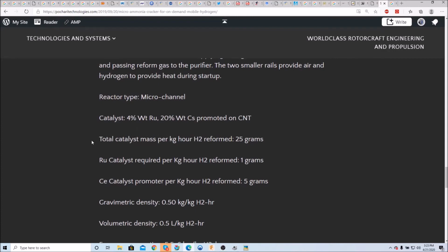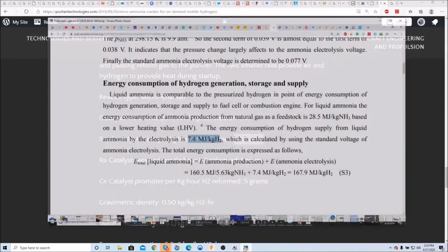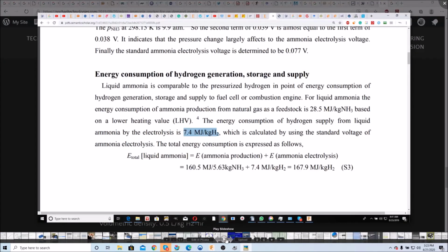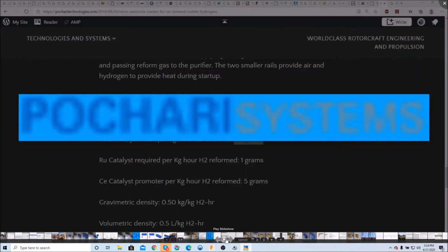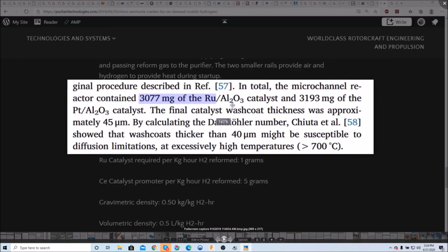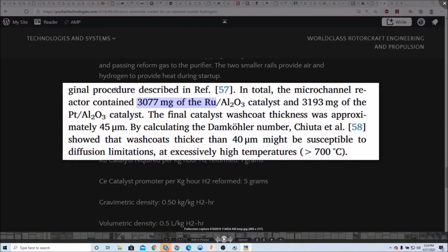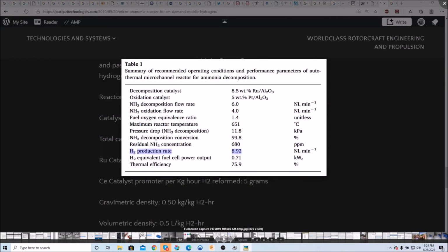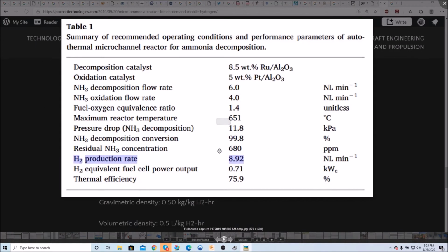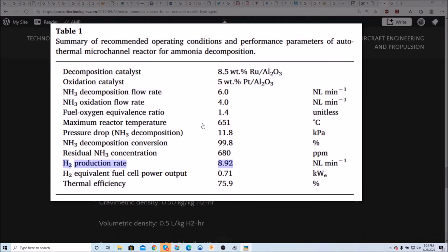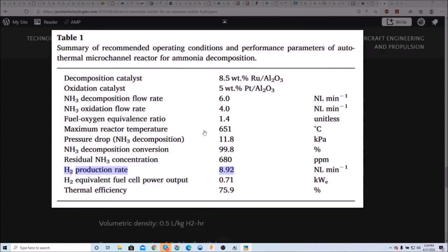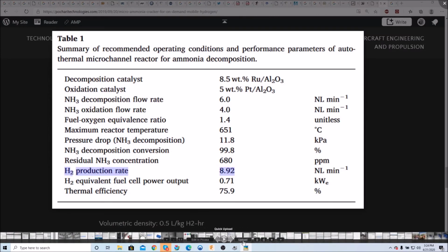And this number here, total catalyst mass per kilogram hour H2 reformed, 25 grams, that's simply based on the numbers that I have. Take the data for the microchannel ruthenium reactor, which we're going to find shortly. So, 3,000 milligrams, and I just computed the flow rate. So H2 production rate, 9 normal liters per minute. So yeah, you just go by that data and compute it.